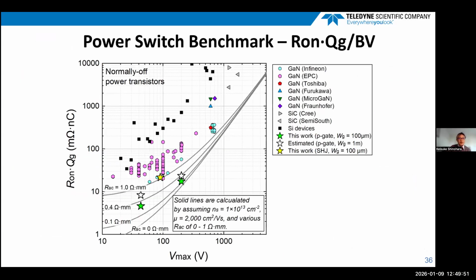So here I show the power switch figure of merit benchmarking, which is R-on times QG, plotted as a function of breakdown voltage. Our p-GaN gate HEMT shows about 3 to 5 times better performance as compared to the best GaN-on-silicon power switch devices reported previously. We also showed good performance of the super heterojunction devices, while there is still a big room to improve the breakdown voltage in the super heterojunction devices.